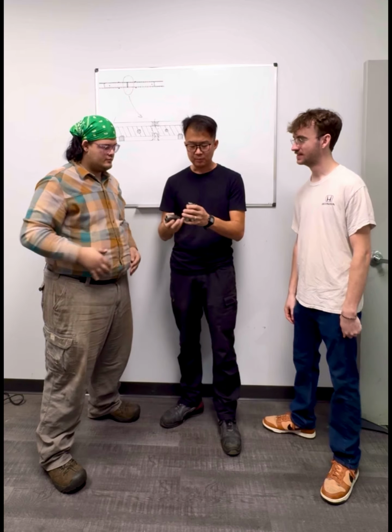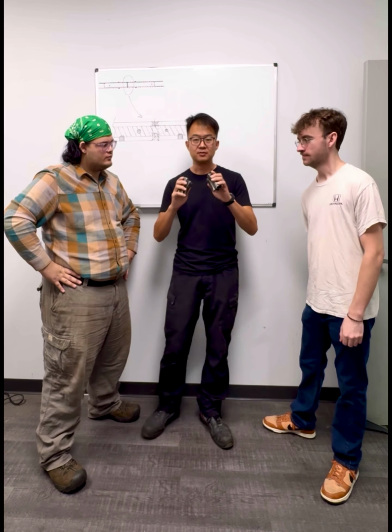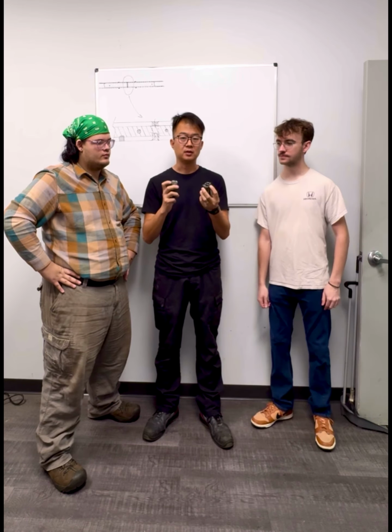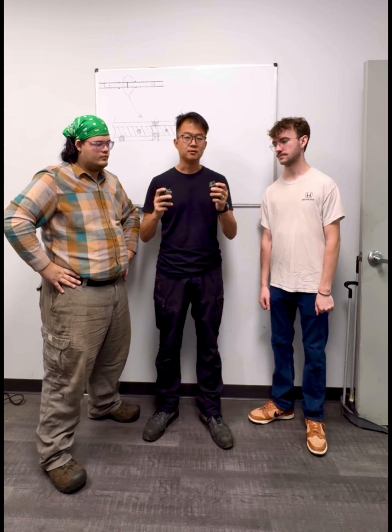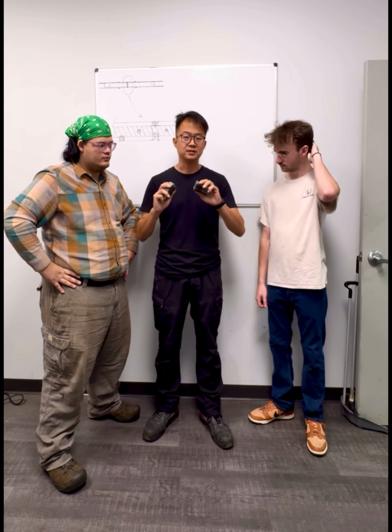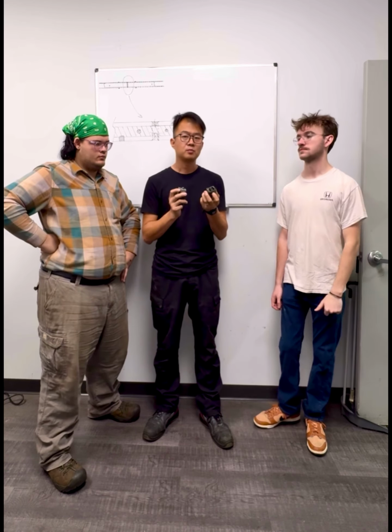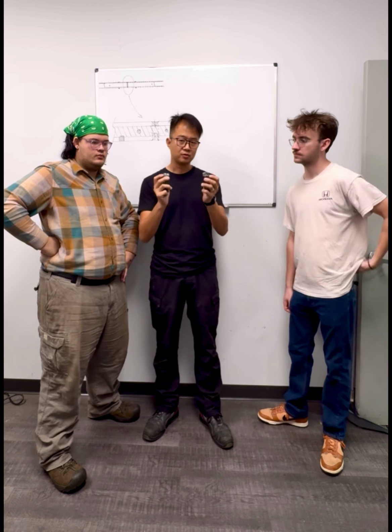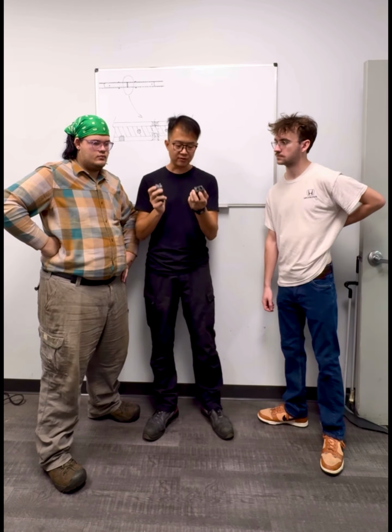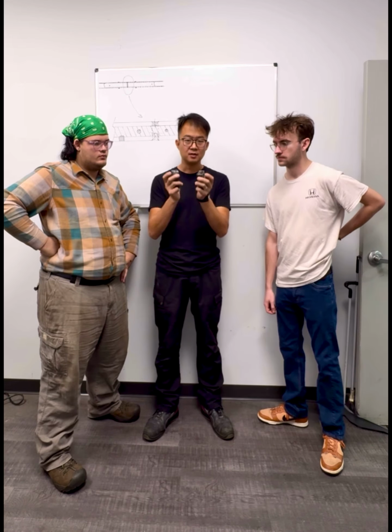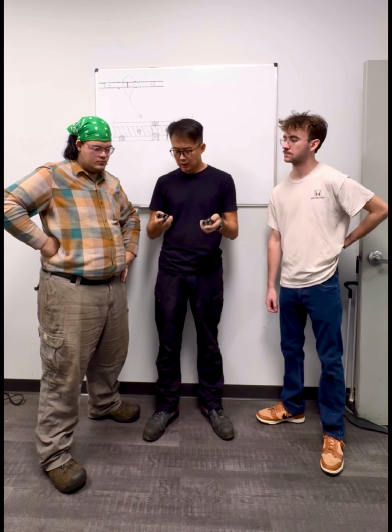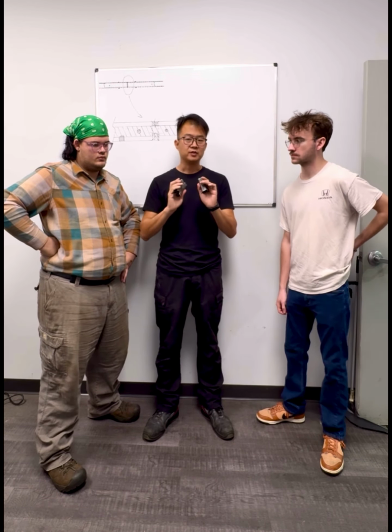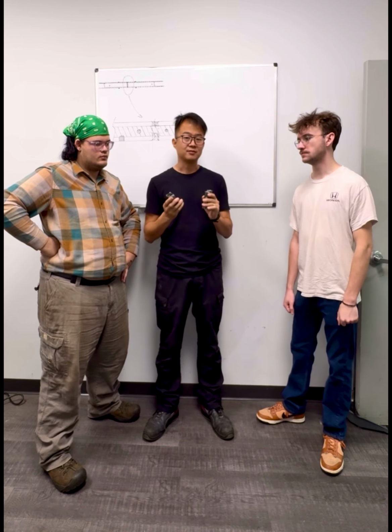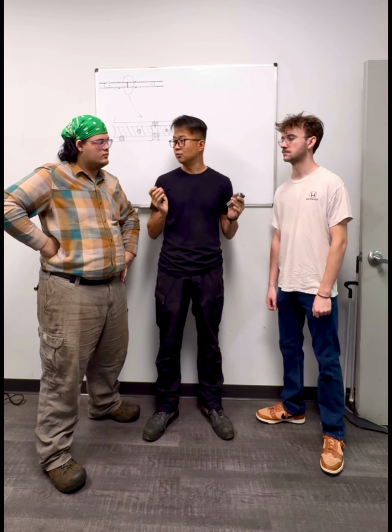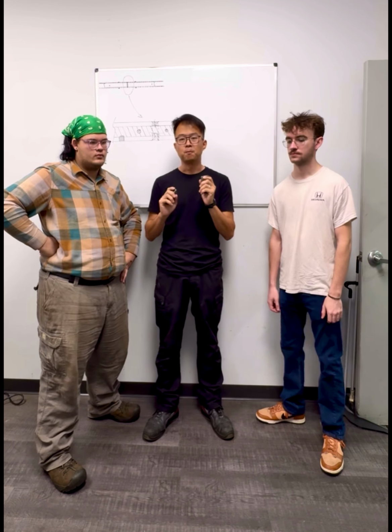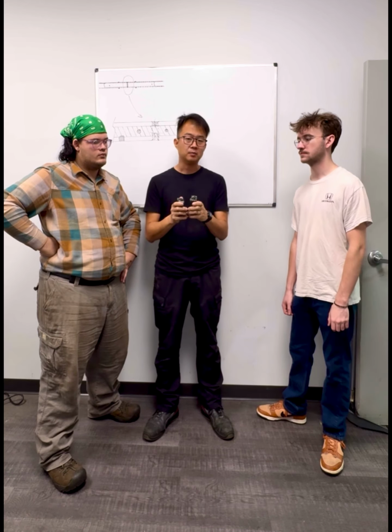Okay, so with the test result, I believe that instead of a repeated very light load that most race cars are going to suffer from, say over 50 hertz of vibration for such an extent of time, this is more simulating a higher load, more toward when an impact happened. And the good thing we found out is, regardless of layout, the weld is not going to be the weakest link. The plug welds hold in place really well, even though I'm expecting there's relative movement between the inner and outer tubing. By the way, they are really tight tolerance and pressed in together. So they still fail at the same time.